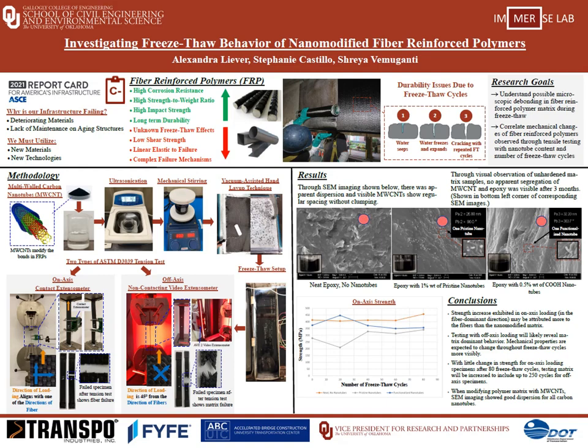Scanning electron microscope images shown here show apparent dispersion of the nanotubes in the matrix. No clumps are visible, which can be a challenge when working with carbon nanotubes. The graph shown here shows strength of the FRP over 80 freeze-thaw cycles tested on axis.